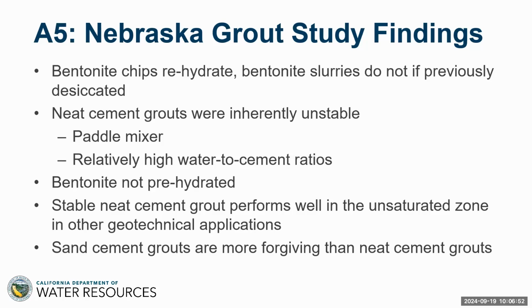Interesting study finding there that the bentonite chips rehydrate, whereas the bentonite slurries did not if previously desiccated. So that's important, but that may be related to the fact that the heavy bentonite slurries were not prehydrated for long periods and were mixed in the paddle mixer. So there's a little reevaluation to be done there. The bentonite certainly was not prehydrated.